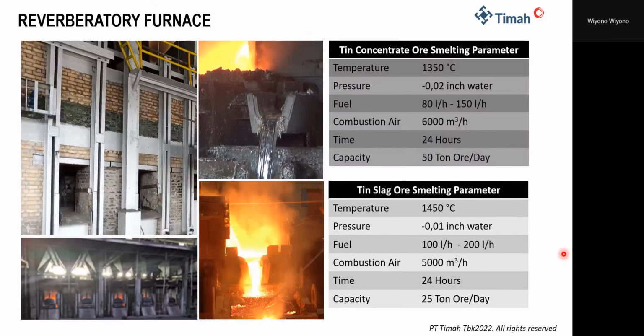And then below, this is the process of tin slag smelting. We smelt the first slag in the second stage. You can see from the picture that the color is brighter. It means the temperature is higher than the first smelting stage. The temperature that we need is higher, around 1450. The pressure is lower, and the fuel is higher because we need a higher temperature to smelt the slag. Combustion air is below. Then the process time is 24 hours to smelt 25 ton of first slag.